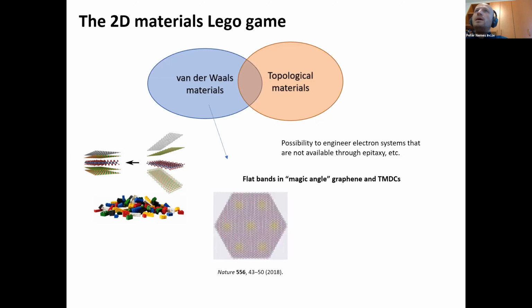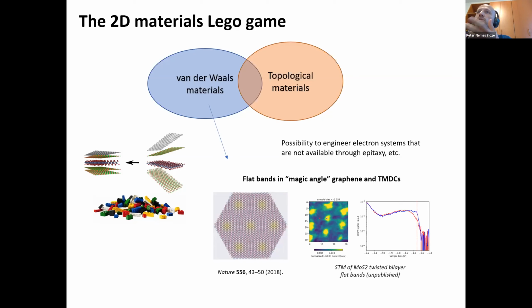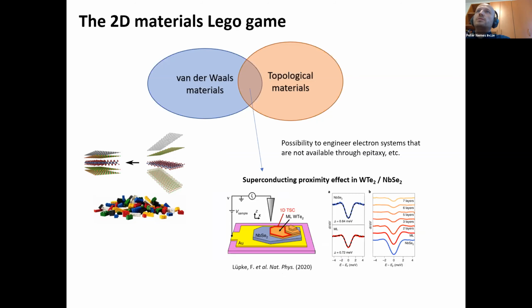And one of the most interesting and simplest examples of this is of course this magic angle graphene that we heard about in the talk of Pablo Jarillo-Herrero in the beginning of this conference. Also, you can do this twisting, this twistronics kind of thing with transition metal dichalcogenides. So this is just a snapshot of some new results from my group, where we've shown that you indeed also get these flat bands in twisted molybdenum disulfide bilayers. So this physics is ubiquitous basically in the TMDCs as well. But if you turn to topological materials, you can also do this kind of stacking if you have 2D topological materials.